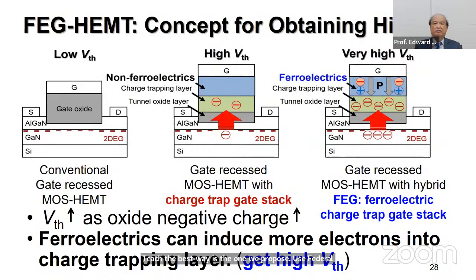In this way, in the charge trapping layer, you can have electrons over there, which is negative. And because the charge trapping layer is negative, your polarization will point downward. So in this way, the ferroelectric can induce an electric field that is opposite to the voltage you applied. And in that way, you have to apply an even higher voltage to turn it on, so you can get very high VTH. So the ferroelectric can induce more electrons into the charge trapping layer, and you can have very high VTH by this arrangement.